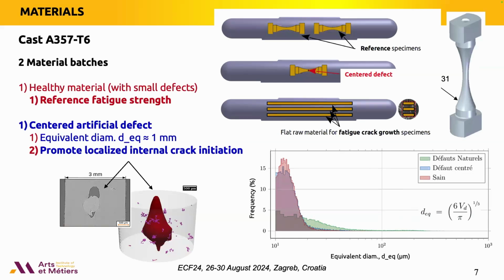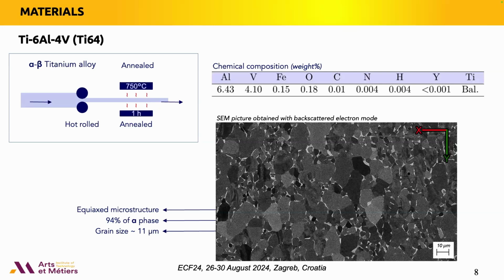I will not present those; I present only the results about the other materials, which are specimens in a titanium alloy. So again, this is a titanium alloy which is very well known in literature. This is the TI-64. It has been obtained by hot rolling, and after we have applied an annealing treatment. So this is a classic alpha-beta microstructure. Most of the microstructure is the alpha phase, around 94%, with a grain size which is much smaller compared to the other alloy, around 10 micrometers.